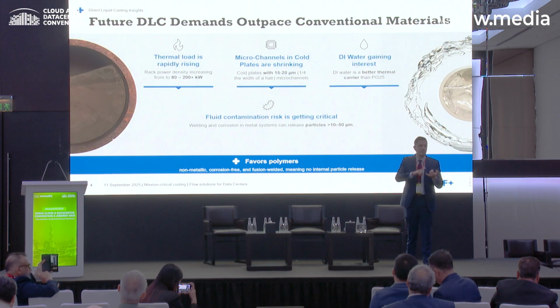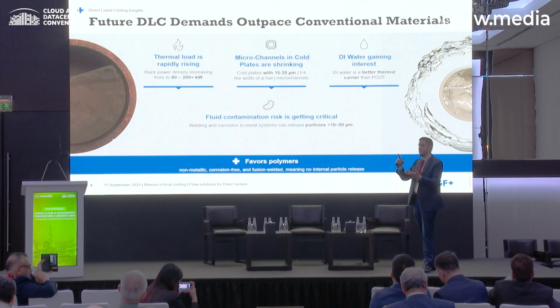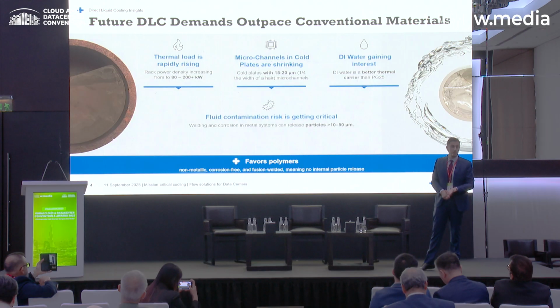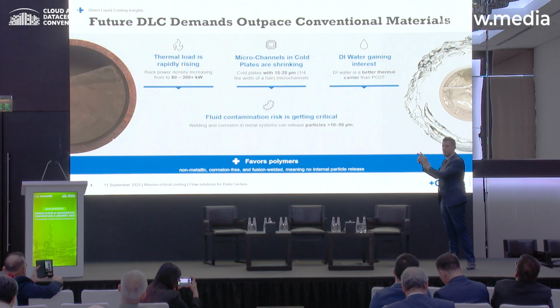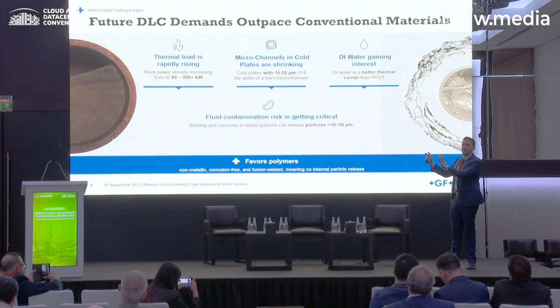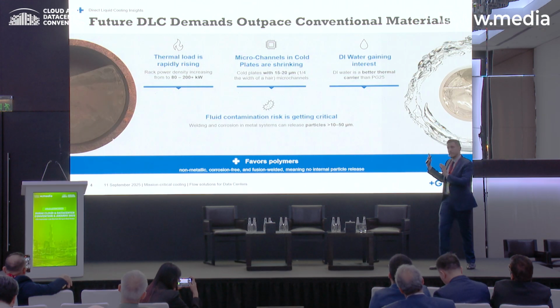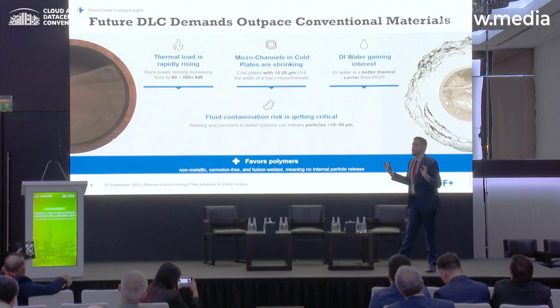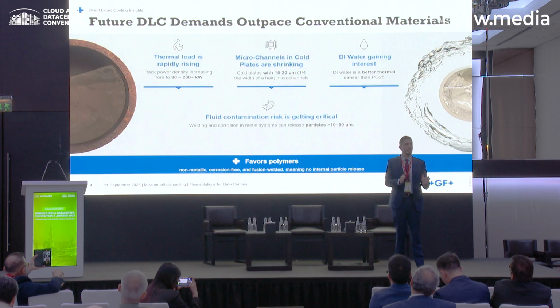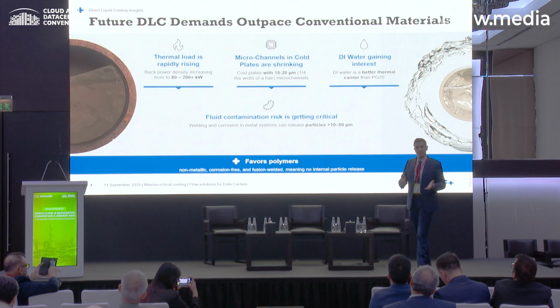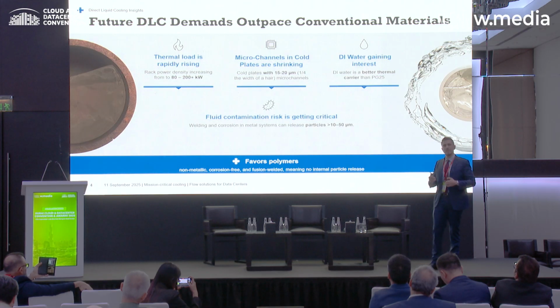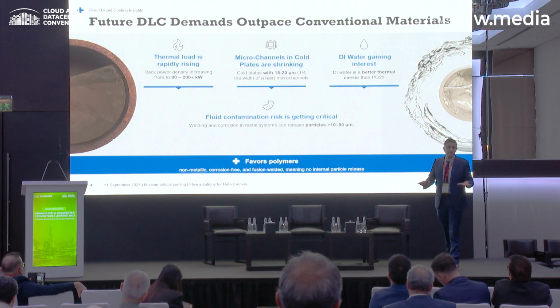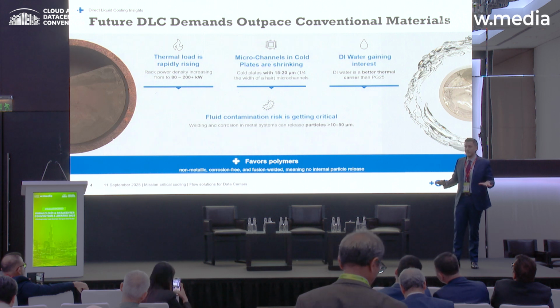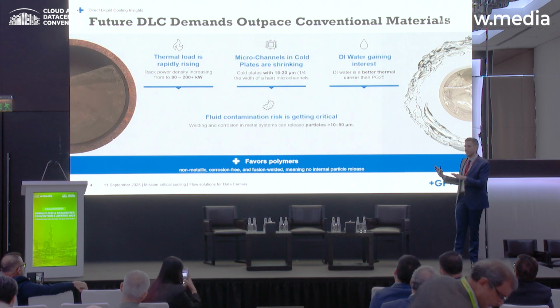This contamination results from welding, from scaling, from corrosion, and yes, stainless steel can corrode, can block these channels and can interrupt the cooling process. Deionized water showed to be a serious candidate to partially address the problem. So with deionized water, the scaling problem is somehow eliminated. However, the existing stainless steel system is not supported to accommodate new technologies.